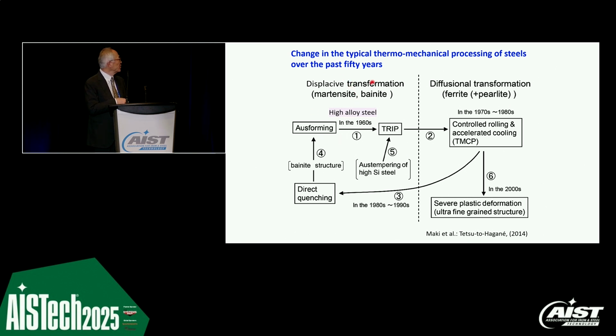So for displacive transformation, we really started from displacive transformation martensite and applying it to high alloy steel for ausforming and TRIP, invented by Professor Zackay in Berkeley. Then after that, all the main steel product goes to thick plate. We apply diffusion transformations, ferrite, pearlite, by applying controlled rolling and accelerated cooling in the 70s and 80s. Then again, we go back in the 90s and 2000 to direct quenching and also the